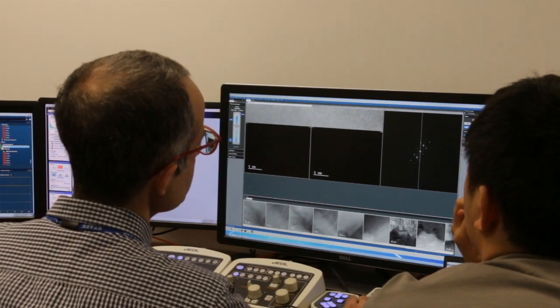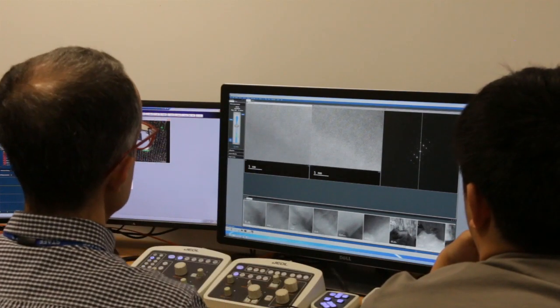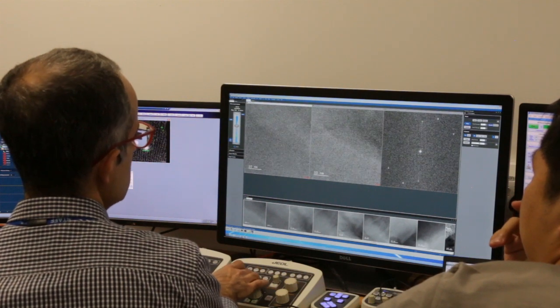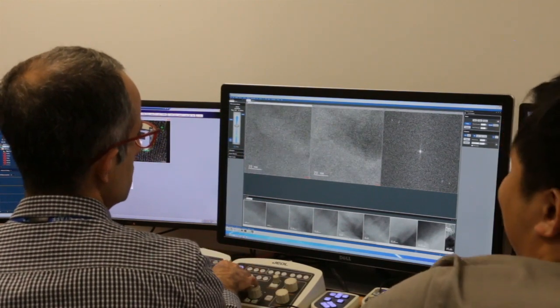I've been coming to Diamond for many years to do experiments using the synchrotron. Today I'm using one of the EPSIC electron microscopes, working on corrosion of zirconium alloys used in the nuclear industry. Zirconium alloys are the preferred fuel cladding alloys in pressurised water reactors — they separate the coolant water from the uranium dioxide fuel. You really don't want the water and the fuel to mix, so the zirconium has to be very corrosion resistant and survive in the hostile reactor environment: hot, high pressure, and with lots of neutron damage. The zirconium does corrode — it grows an oxide layer — and that oxide layer is what we're studying.